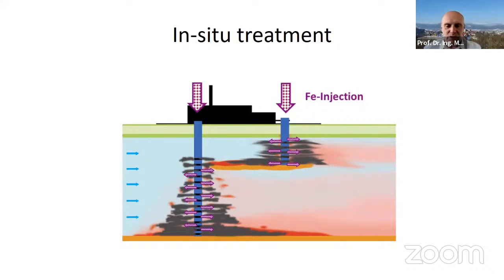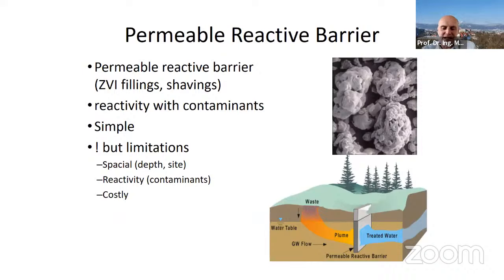The principle which I want to show here is that the contaminated groundwater, which is in red, shows that there is some contamination. We make a drilling, we make a borehole, and we inject something into the groundwater, which reacts with the contaminants there and reduces them to something which is not so dangerous. One of the examples is application of nanoparticles of iron. The principle has been used for many years in the so-called permeable reactive barrier, which is on the picture below, where you construct a barrier which you fill with iron shavings or flakes, something from industry, and this iron is reactive and able to react with contaminants.